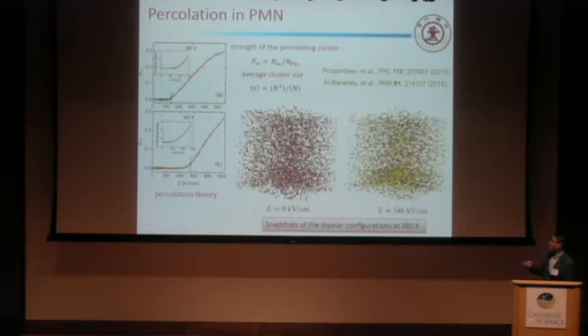This is the 3D snapshot of the dipole configuration at 380 Kelvin. When there is no electric field, we can see... I need to introduce that the green line is along the 111 direction because our electric field is along the 111 direction. When there is no field, we can see the system is not percolating. But when we choose the percolating electric field, we find percolation through the whole supercell.